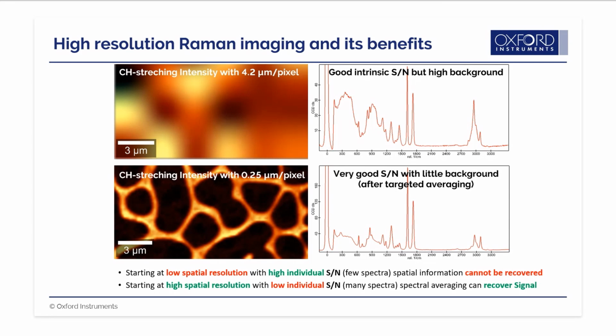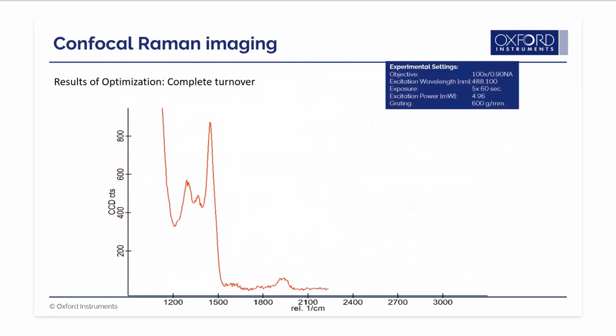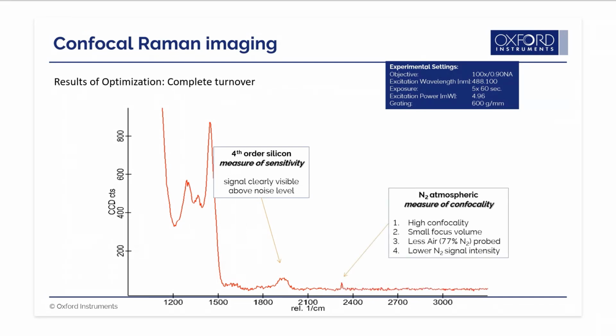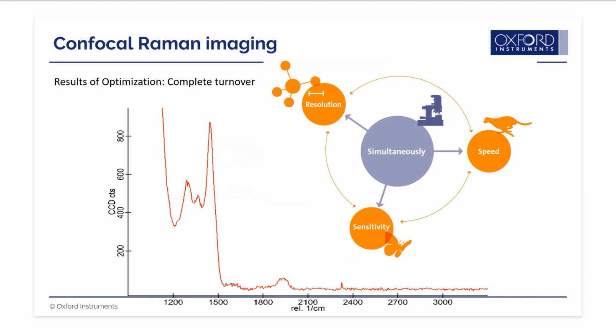A measure for the sensitivity of a confocal Raman microscope is to observe the 4th order of the silicon Raman band at about 2000 relative wave numbers. The band that appears at 2230 wave numbers corresponds to nitrogen from the atmosphere. The intensity of this band is a measure for confocality. So important for confocal Raman microscopy are resolution, sensitivity, and speed that must be achieved simultaneously.